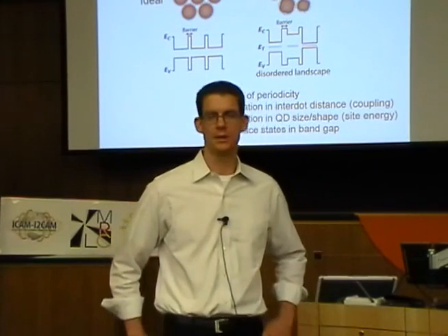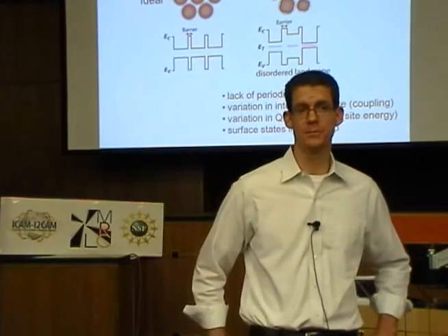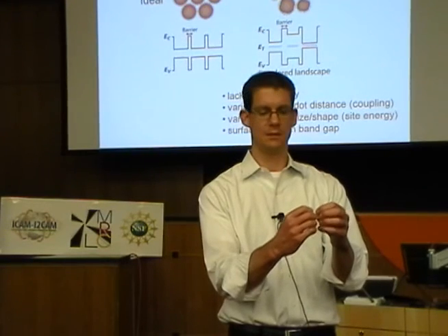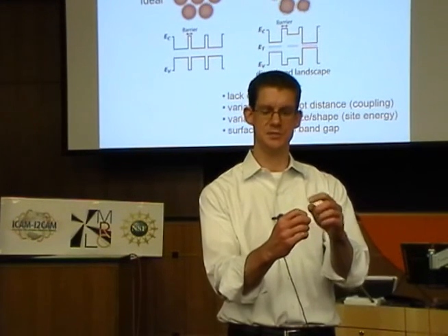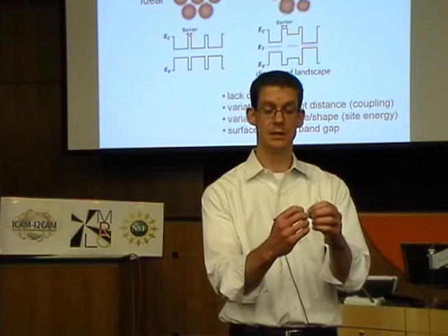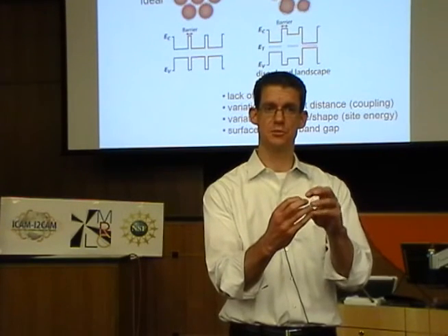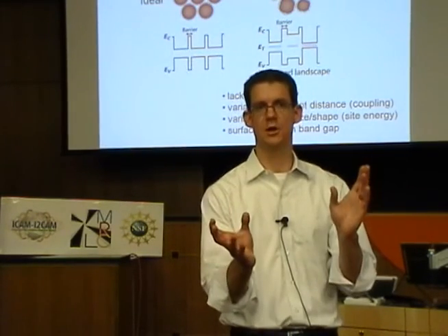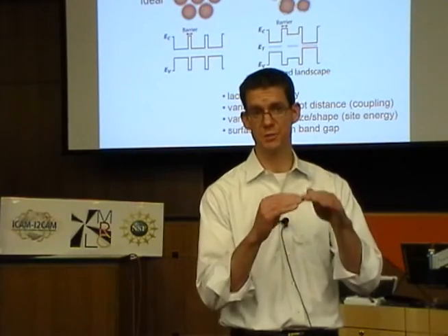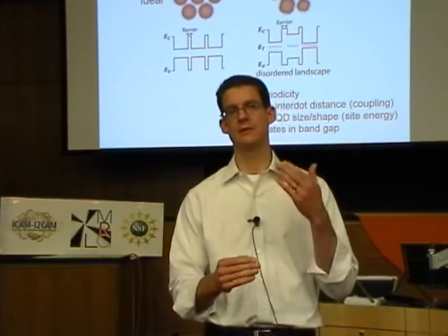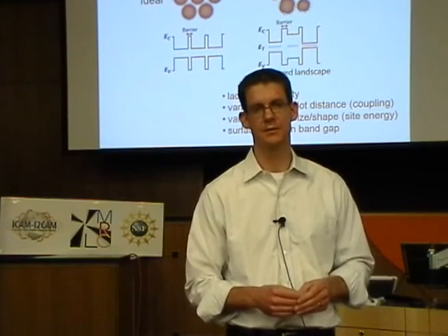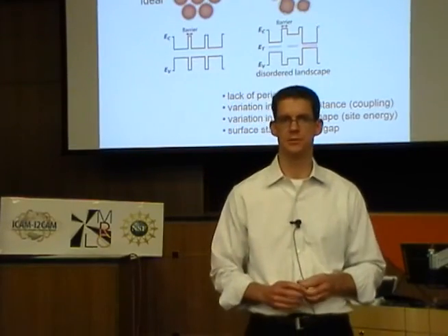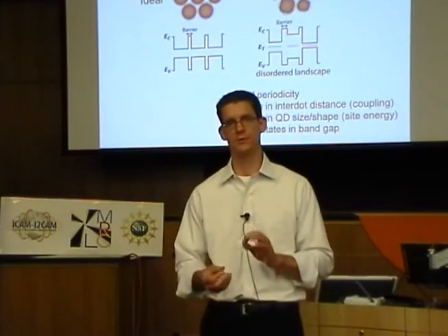It would, yeah. What we're going to find tomorrow is that any disorder that's extreme like that matters. When you have two quantum dots together but not touching, they still behave as, let's say, 5 nanometer dots, just tightly coupled. But when they start necking together and there are physical points of contact, then suddenly the exciton or the electron can delocalize over a much larger part of the structure, and the confinement energy is much, much lower in that case. So if that kind of disorder is present in the system, it can really wreak havoc on mini-band formation. But it depends. You can still have them, but you have to have very strong coupling.